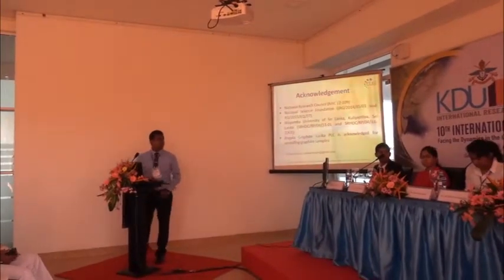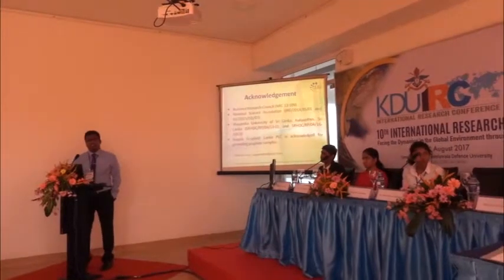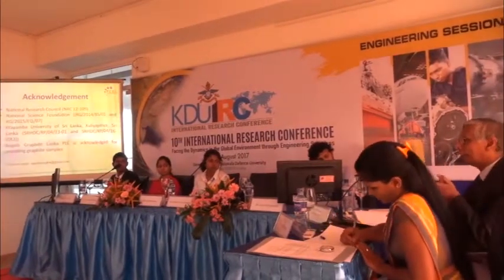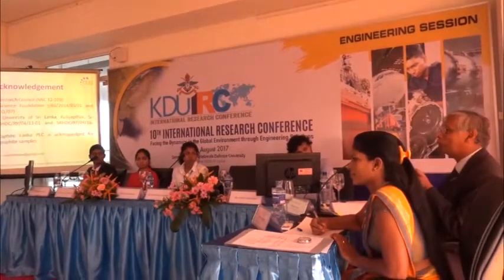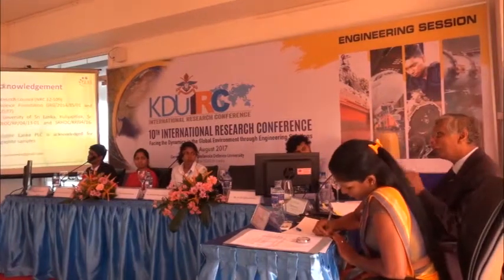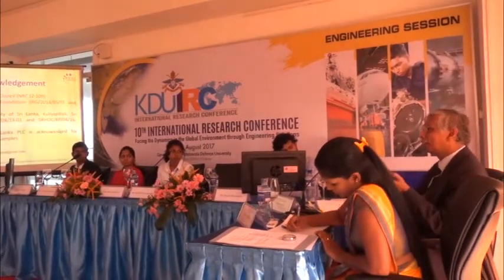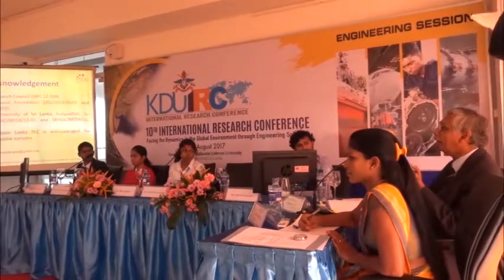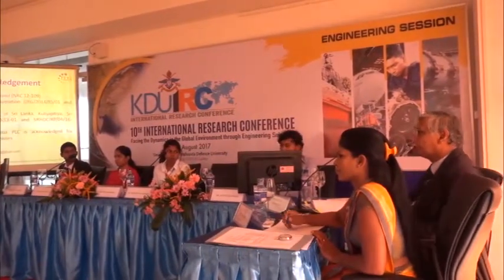The subject is open for discussion. I will start. Now, using open circuit voltage 1.03 volts. I don't know what particular battery, but if you take a lead acid battery, the open circuit voltage could vary from less than 12 volts to 13.6 volts. Immediately after charging, before disconnecting, it will probably be something like 13.64, and immediately after disconnecting, the open circuit voltage would be something like 12.8, and depending on the state of discharge, the open circuit voltage is a variable. So when you say 1.03, at what stage of charging is that open circuit voltage?